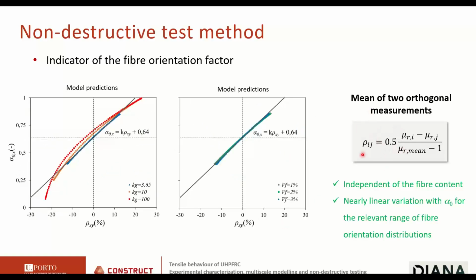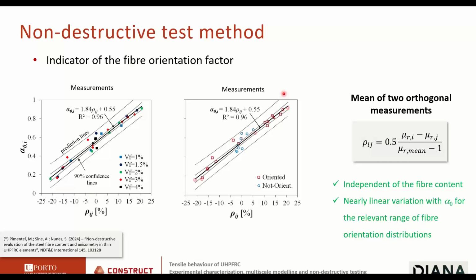So what we want is to relate this now with the fiber orientation factor. This is what the model says. So the relation between this indicator and the fiber orientation factor that we need is like this. If we use a range of fiber orientation distributions closer to what we can find in practice, we see almost a linear trend. And this is actually what we observe. So we can find a linear relation between this fiber orientation indicator and the fiber orientation factor.